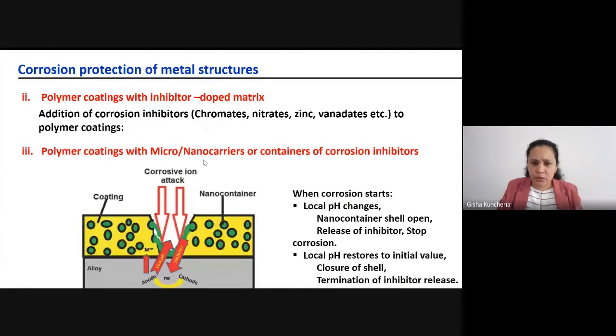So in this case, what we are doing, we use some nano or micro carriers or containers of corrosion inhibitor. Here, the picture shows the polymer coating mixed with this container carrier. So this nano container contains the corrosion inhibitor, and these containers are sensitive to pH change. When corrosion occurs on the metal surface, the pH of the local area will change. So these containers become active and they will open up, release the corrosion inhibitor, and stop the corrosion. So this is another method.